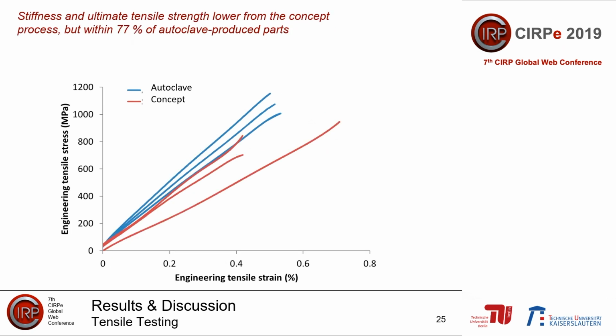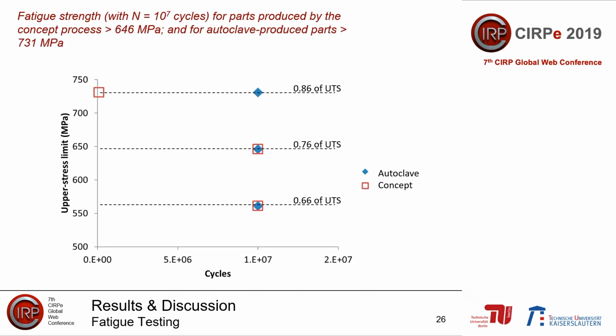In terms of the tensile testing, it's a similar story. Parts produced in our process have around 80% of the tensile strength of parts produced in the autoclave. In terms of fatigue properties, again, it's a similar story. So parts produced in the autoclave exhibited fatigue strength given a fatigue life of 10 to the 7 cycles of more than 731 megapascals. In our concept process, more than 646 megapascals.